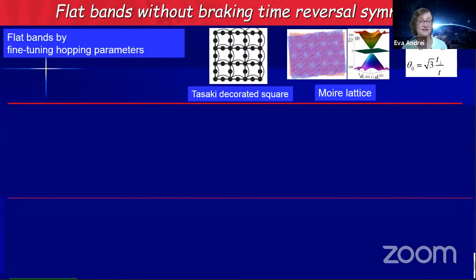So there are several strategies. We can create it by strain, which creates pseudomagnetic fields. We can create it by fine-tuning competing hopping parameters. For example, nearest neighbor hopping and next nearest neighbor hopping give you a geometrically induced flat band. We can do it, and this is what I'm going to talk about, by superposing two graphene layers and creating a Moiré lattice. Here you have a competition between hopping within the layer and between layers, intra- and inter-layer hopping. And when the two are roughly comparable to each other, you get an almost perfectly flat band.